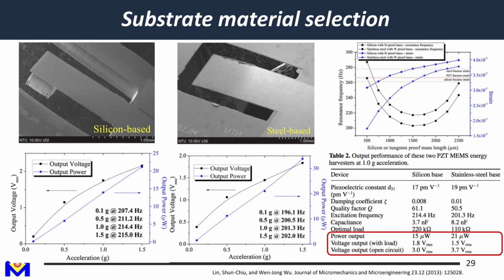So it's very important. When we combine a piezoelectric ceramic onto a stainless steel substrate, it's like reinforced concrete. You have steel inside the concrete to sustain the tension force. Ductile material can sustain tension force and compressive force. But brittle material can only sustain compressive force, but not tensile force. This is why for reinforced concrete used in general buildings, we need to have steel inside the concrete. The combination of stainless steel and piezoelectric ceramic is also the same. With this combination, we can sustain tensile force, unlike silicon plus PZT.